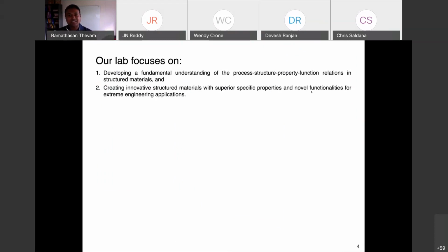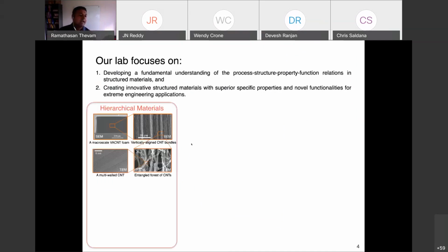There are three classes of materials that we focus on. The first one I call hierarchical materials. For example, you see a carbon nanotube foam. That is a macroscale foam, but if you zoom in to the mesoscale, you have these vertically aligned bundles, and if you zoom in further to the microscale, you can see this entangled forest-like morphology, and you look at one single nanotube, that's a multi-walled carbon nanotube in the nanometer scale. So across these length scales from nanometers to macroscale, you can tune these structural features to affect the bulk properties.